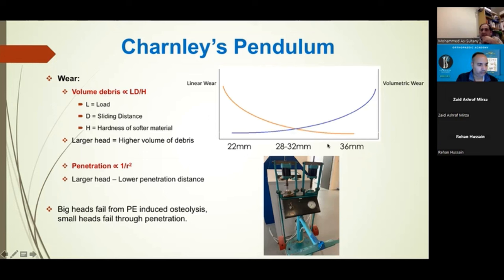get more linear wear, and somewhere in the middle, sort of 28 to 32 millimeter heads, is thought to be the most ideal in terms of compromise between the two. So with big heads, you're thinking that failure is due to the amount of osteolysis from the polyethylene that's created, because of a lot of volume. And with small heads, it's more potentially penetration through the material that could result in failure, thinning of the material as you penetrate through it. So just a little thought about that.